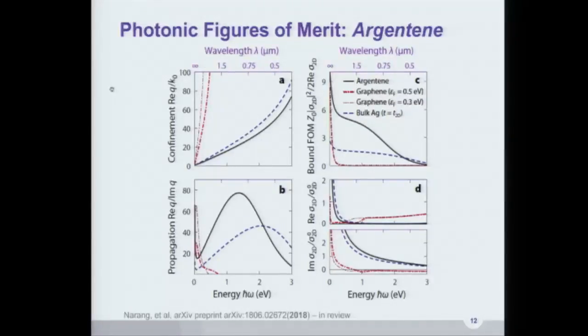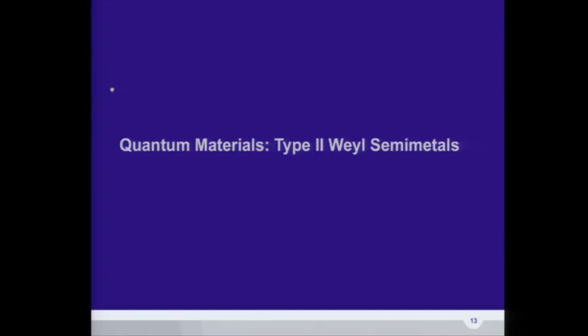Okay. And we predict that Argentene outperforms not only graphene, but graphene at a couple of different dopings. So this is comparing the fact that graphene, once you start doping it, is no longer that magical low-loss material. In fact, even at a 0.3 or 0.5 eV shift of the Fermi level, and this is actually assuming that you gate it, not that you explicitly chemically dope it, we see that with Argentene, you can really get the longest propagation lengths, particularly in the visible, where there is this paucity of materials that are simultaneously low loss and have the ability to couple in the visible. All right, so that was the 2D case, okay?